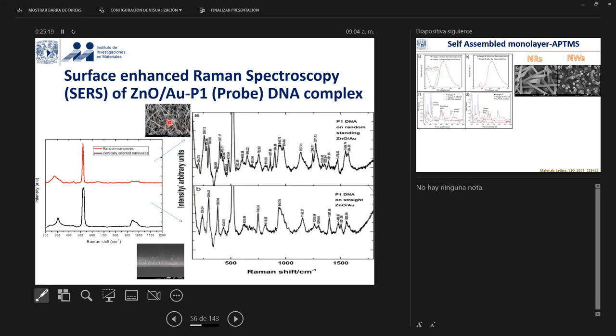Why? Because in this case, we have random nanowires with gold on the tip, and when we are doing the Raman or SERS characterization, we have more enhancement in the signal due to electromagnetic effect and chemical effect. Gold has surface plasmon resonance, the SPR effect. Finally, the whole system has a resonance that increases the signal of the interaction with the analyte. So the benefit in this case is that we have more electromagnetic and chemical enhancement, and this particular system is better for optical biosensing.